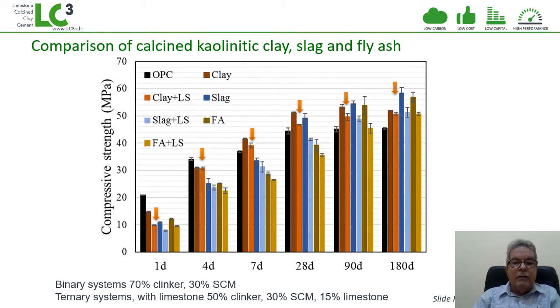You can see here how these systems compare with other supplementary cementitious materials. And please bear in mind that we're dealing here with binary systems where you have 70% clinker, and in the ternary systems, you have 50% clinker. One thing I can prove here is that clinker content is not so important as in any other of these pozzolanic cement cases. And this is because of the synergy between the calcined clay and the limestone and the new products that are formed that contribute to strength, as we're seeing here.